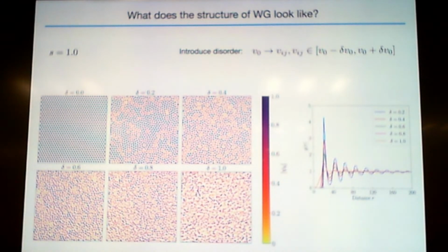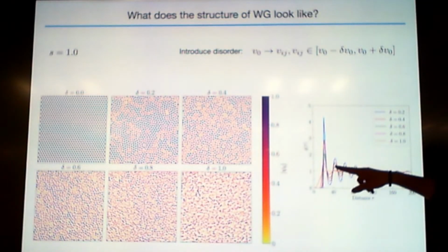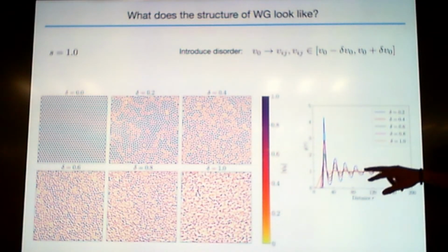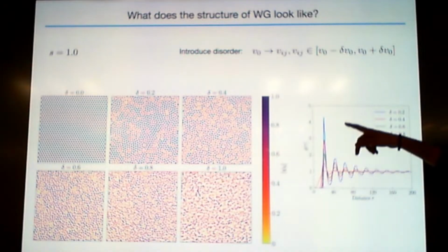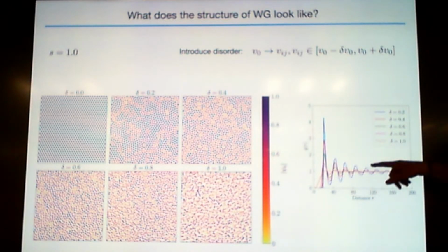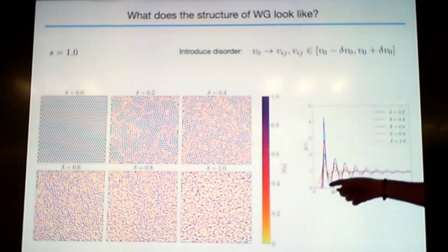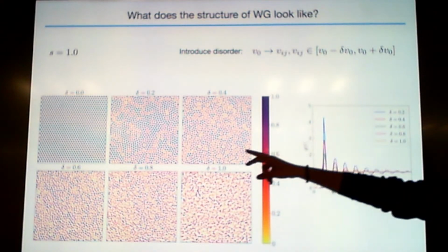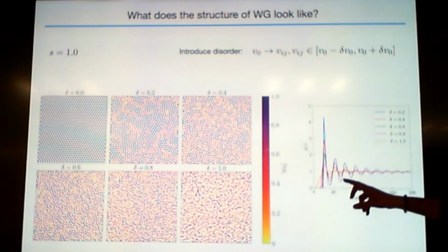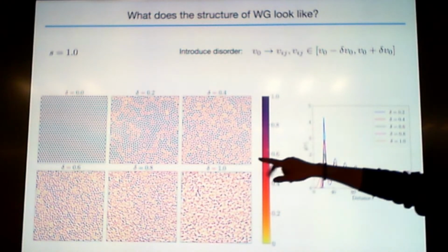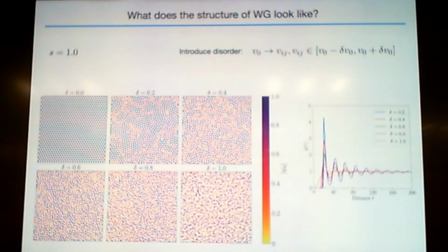But overall, the picture is, as delta increases, your disorder increases, also measured by G of R. The highest delta has almost no structure and almost no fluctuations. The lowest delta, 0, corresponds to Bragg peaks, but delta equals 0.2 and 0.4 are basically frozen systems with some defects, grain boundaries in it.